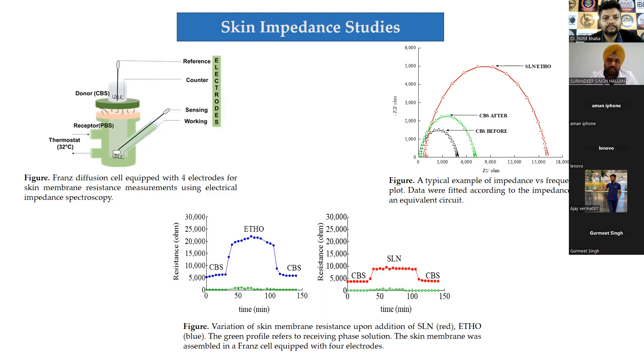This means these formulations have a reversible connection with the skin membrane. They need time to blend with the skin lipids, and while they stay at the skin surface, they can block movements of solutes and other molecules. The resistance was higher in the case of ethosomes because they are very flexible, due to the phospholipid content, and highly interactive with skin lipids — resulting in better blending and higher recorded resistance.